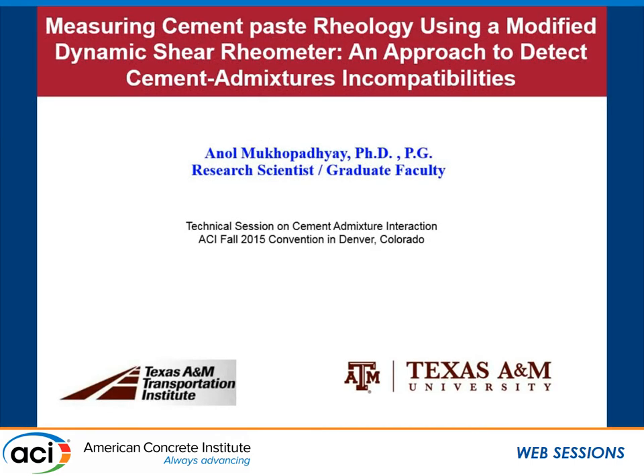I will talk about a dynamic shear rheometer that is commonly used by different DOTs. The main purpose of this device is to characterize viscoelastic properties of asphalt binder. This project I got from the Texas Department of Transportation. The idea was: can we modify the dynamic shear rheometer to measure cement paste rheology? As this is a very commonly used technique by different DOTs, the device is available, so we can increase the versatility of that particular device to measure both asphalt and cement — a practical, relatively inexpensive technique that can be used in the field to measure cement paste rheology before concrete is placed, detecting any abnormalities within one to two hours so that you can still fix the problem and place the concrete.